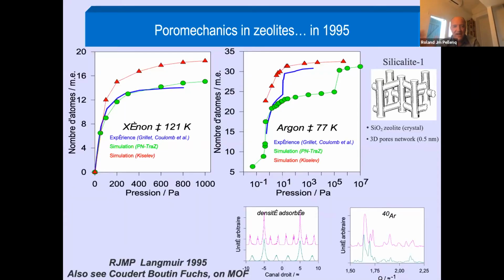And then my last slide will be about the zeolite stuff, and this is my encounter with poromechanics in 1995, where I was trying to simulate this curve of argon with the step in the adsorption isotherm, and I didn't get anything. That's my green point, when they were shifted by a lot of magnitude, and that was not a swelling, by the way.